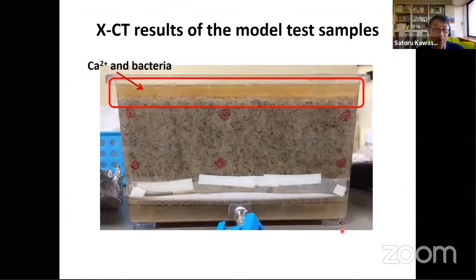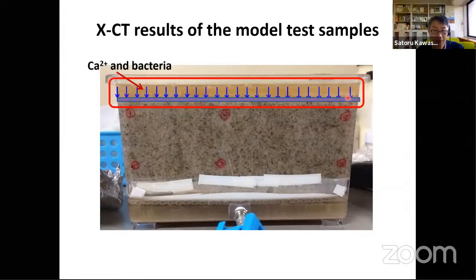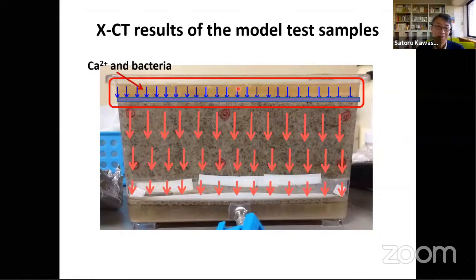And this one, we try to solidify this area. This one consists of mainly silica sand. And not only this area, but also bacteria exist, not only in the sandy material, but also in this water solution area. So calcium carbonate precipitated not only inside the sandy material, but also in these solutions. So little by little, precipitated calcium carbonate penetrates from the top of the surface. That's why the estimated UCS is higher than the lower portion.